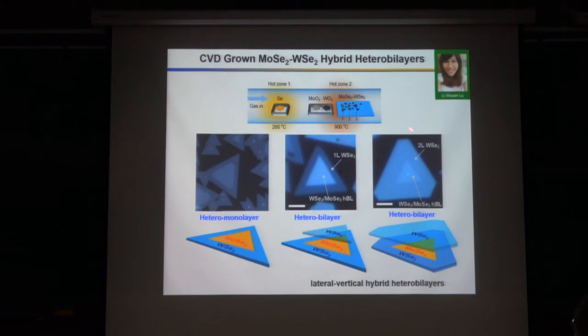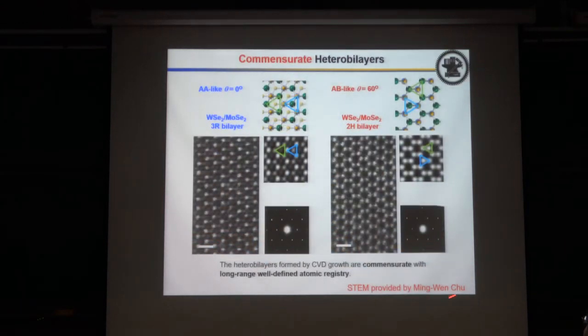So we can use growth to control this kind of lateral or vertical structure. Here is a vertical bilayer structure. This is also a bilayer structure. And we also asked Ming-Wen Chu to provide STEM images. So he confirmed that this is a commensurate structure with perfect atomic registry in the bilayer. So we can have so-called R-type stacking with the same orientation, and this is H-type stacking with the opposite orientation, so the stacking angle is 60 degrees.